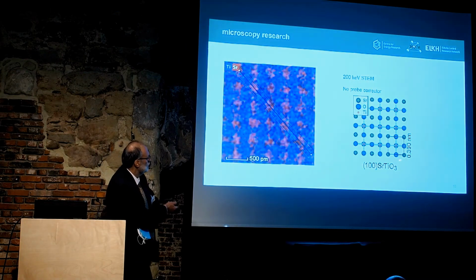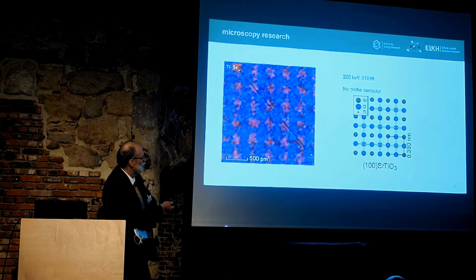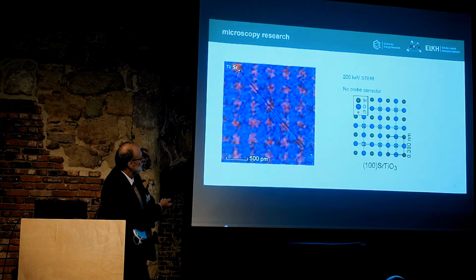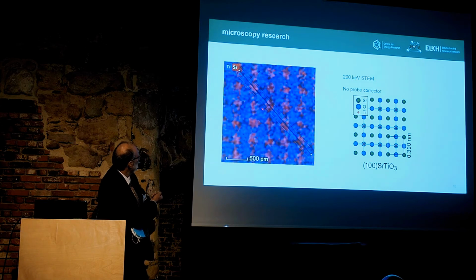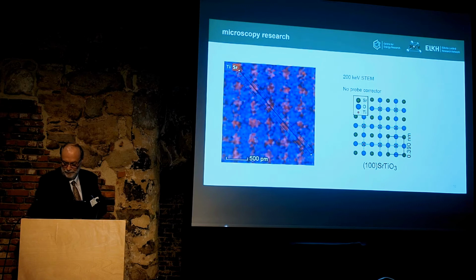And now with the new microscope, there is a crystal, strontium titanate. Here you can see the position of titanium and strontium. And at the atomic level, we can distinguish the titanium and strontium.